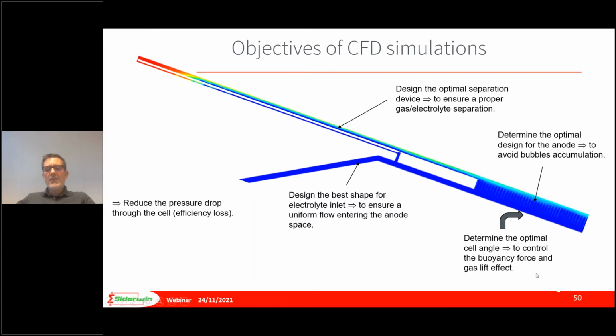One of the main objectives was to determine the optimal cell angle. So we have decided to put an angle in the cell to enhance the buoyancy effect of the bubbles and to remove the bubbles from the domain. We had also to determine a very optimal design for the anode, so as to avoid some bubbles accumulation in the anode. And finally, we had to define the optimal separation device in this area to be able to properly separate the gas and the electrolyte in the cell.